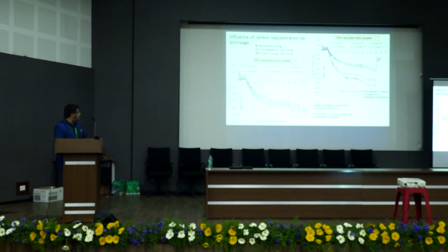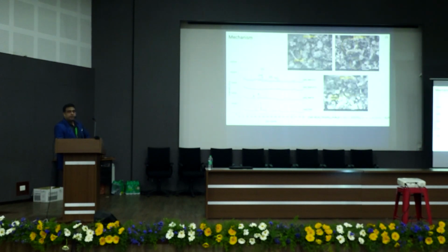And why does that happen? Well, again, we did some X-ray investigations and microstructure investigation using AFM. What we see is that the 25% RBP, non-carbonated, contains a lot of ettringite around the brick powder crystals or in general in the bulk matrix. But when we carbonate it, we don't find much ettringite precipitate. Instead, we see some small crystals, about 2 to 3 microns in size, of calcium carbonate being deposited.